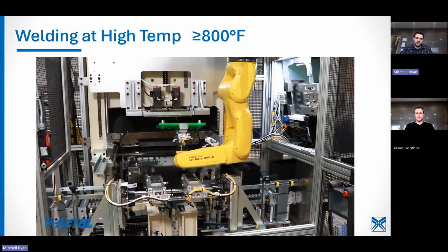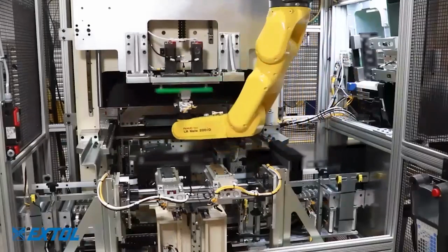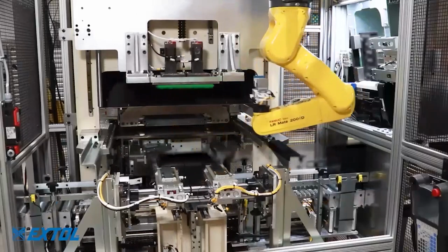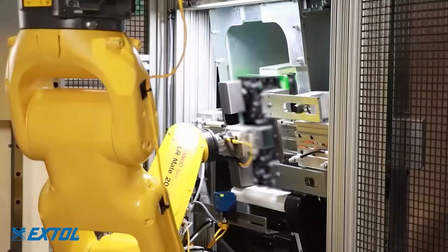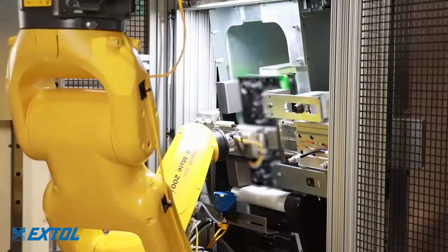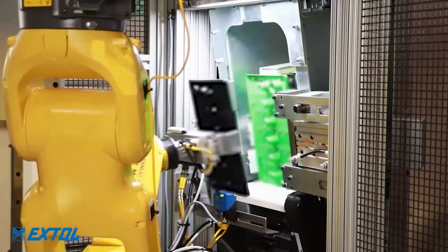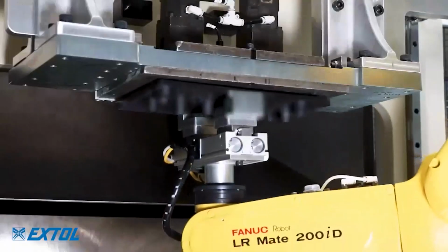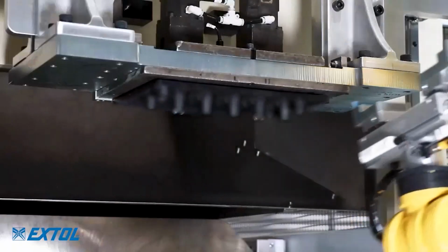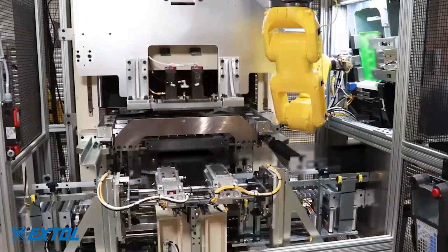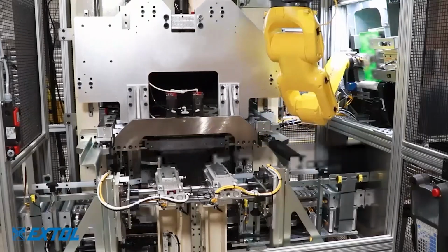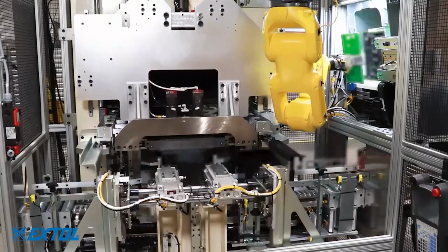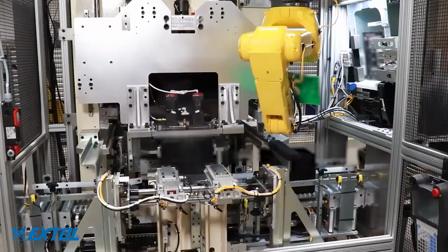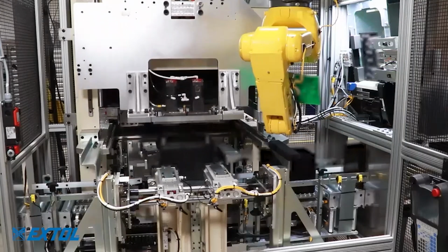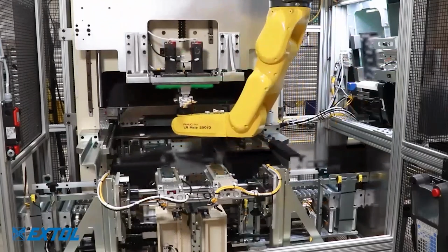We typically weld, so for hot plate, a lot of the materials we deal with, this is a polypropylene application, will weld at 800 degrees Fahrenheit plus. And that helps with a couple things. At higher temperature, you're reducing your cycle time. That's one of the benefits. The other one is if there's material that builds up on that plate, it'll burn off. So you won't have to constantly maintain and scrape off the plate.